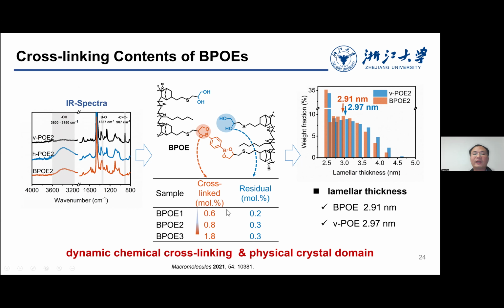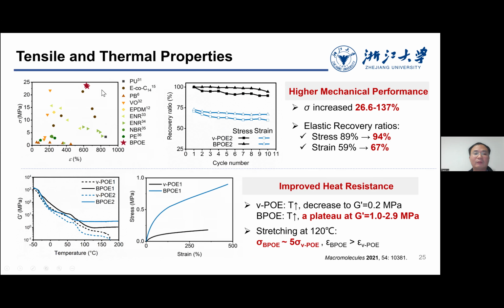But in this way, we can get a synergy between the chemical cross-linking and also the physical crystallization. So in this way, we have developed a higher performance polyolefin elastomer. You can see here, they have higher mechanical performance. Their fracture strength can be increased by 26 to 137%. And their elastic recovery ratio after cross-linking also can be increased from 89 to 94%. And the most important thing, they also have improved heat resistance.